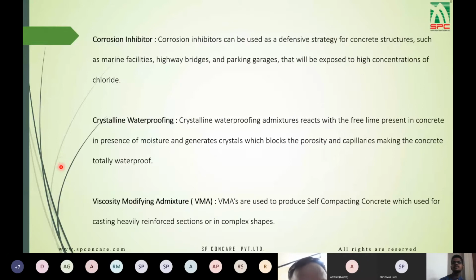The next is corrosion inhibitor. The corrosion inhibitor can be used as a defensive strategy for concrete structures, such as marine facilities, highway bridges, parking garages, or those that will be exposed to a higher concentration of chloride. So what happens? When we add a corrosion inhibitor admixture to the concrete, it forms a coating around the reinforcement of the concrete. So when it is subjected to a higher concentration of chloride or corrosion causing chemicals, it protects the reinforcement of the concrete.